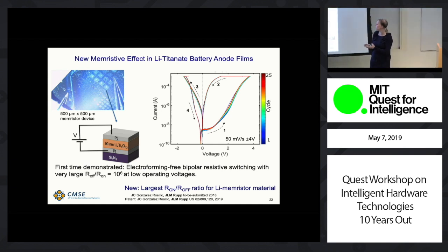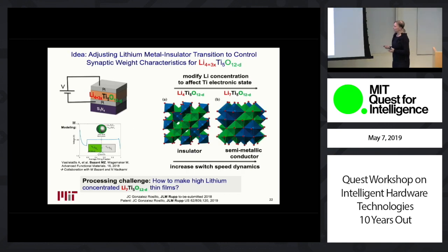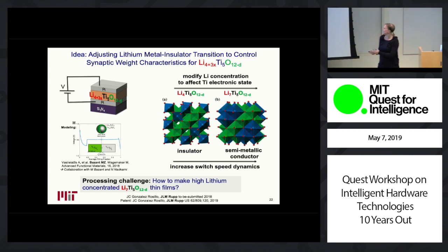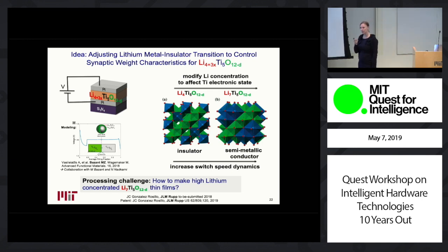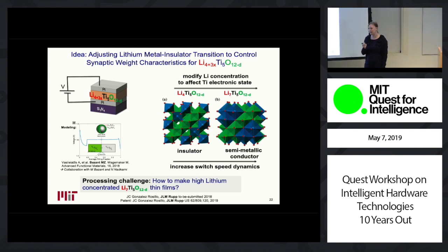So it's actually a new material that we could use for computation. Now, one thing that we asked ourselves: it has a metal-insulator transition. That's actually quite nice. What's really special about the material is that if you have the lithium 4 side here, then it's an insulator. And if I push more lithium into the structure, I can get a semi-metallic conductor.